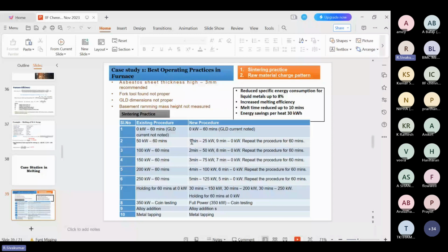For 1 minute, the 25 kilowatt is given, 9 minutes power is off. Repeatedly, it is done for 60 minutes, that is 6 cycles. Next one is 50 kilowatt and 8 minutes. Gradually, the power is increasing and the off timing is reduced. In such a way, we are doing the sintering practices. Finally, we take the full power, and take the alloy addition and the metal tapping.